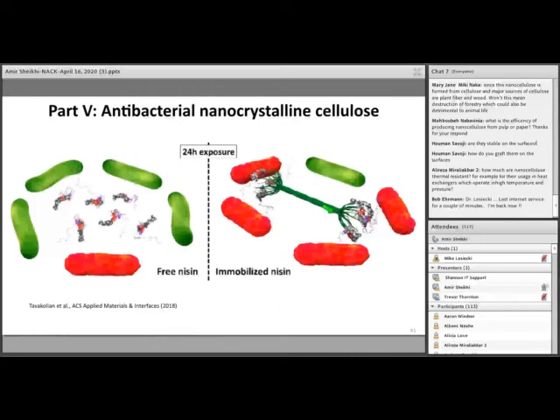Over 24 hours, the stability of these natural antibiotics goes down, and when we functionalize hairy nanoparticles with antibiotics, we see an improved antibacterial performance. And this is work that was recently done in Theo's lab, which is pretty interesting.